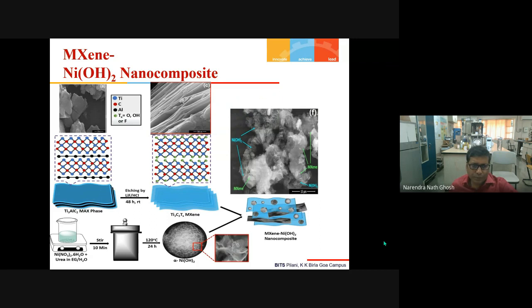Now, the SEM shows that there is no such regular layered structure. We call it Ti3AlC2 MAX phase. Now, by the leaching method, if we can remove this aluminium layer, we are going to get the regular layered structure. You can see that here, after treating with LiF and HCl, these black layers have gone, and it forms this kind of regular layered structure.